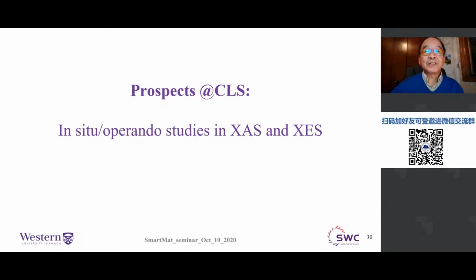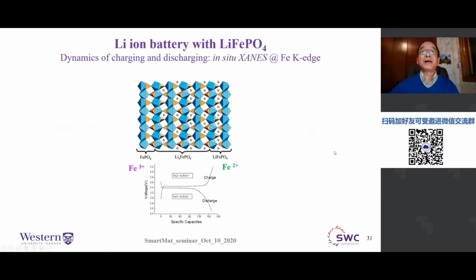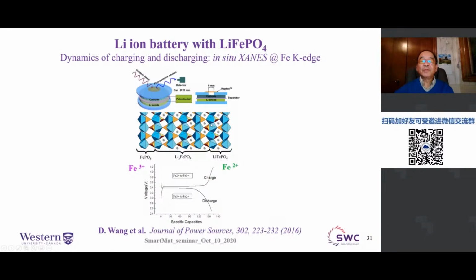In order to understand those things, of course, the best approach is in situ and operando studies, right? We want to track the chemical change as the device is operating, and we can do it with both X-ray absorption and X-ray emission. Let me give you a couple of examples. Obviously, the hottest material in lithium-ion batteries is lithium iron phosphate, where the lithium goes in and out like this. And of course, we can use a simple modified cell to do this kind of experiment.